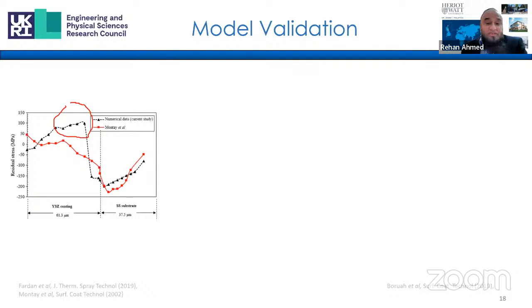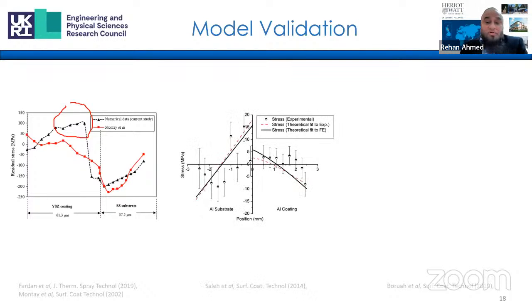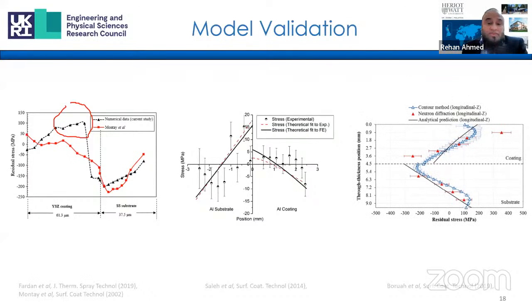The second example compares models between the experimental and the theoretical finite element, and the model is able to predict residual stress to a fair extent, and the experimental work here is obtained using the neutron diffraction technique. The third example uses the destructive contour method, and then compares it with the analytical prediction with neutron diffraction. This work also seems to have fairly good correlation. Obviously, there are some outliers when compared to the analytical prediction, and also differences between the experimental methods due to the inherent differences in the experimental techniques.